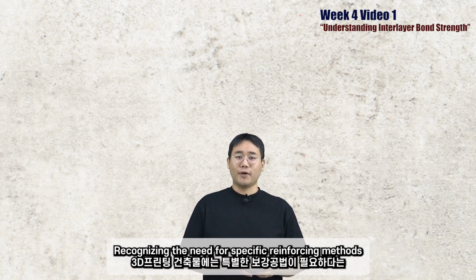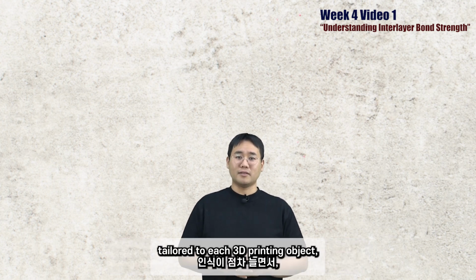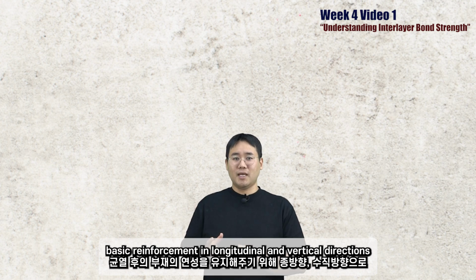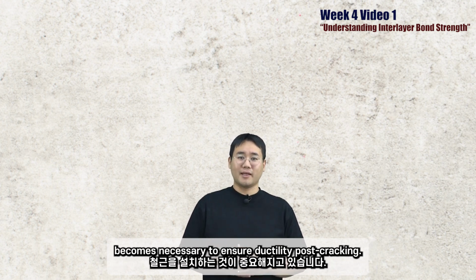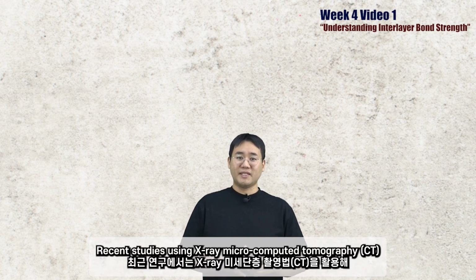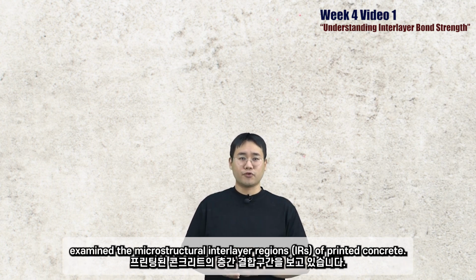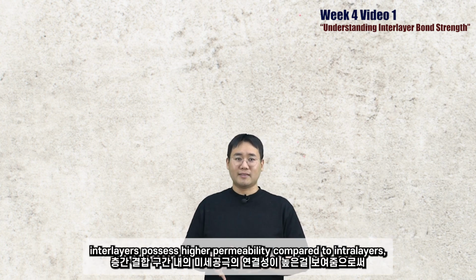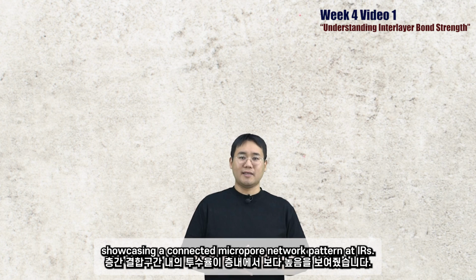Recognizing the need for specific reinforcing methods tailored to each 3D printed object, basic reinforcement in the longitudinal and vertical direction becomes necessary to ensure ductility post-cracking. Recent studies using X-ray microcomputed tomography, or XCT, examine the microstructure of interlayer regions of printed concrete. These investigations reveal that interlayers possess higher permeability compared to intralayers, showcasing connected micropore network patterns at interlayer regions.